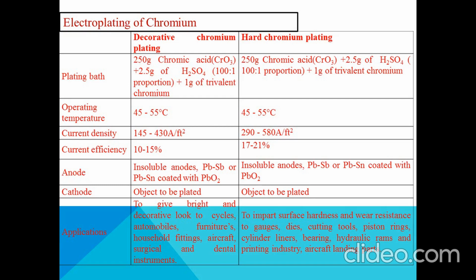In decorative chromium and hard chromium plating, the plating bath contains chromic acid and sulfuric acid mixture in the ratio 100:1. 1 gram of trivalent chromium is also added to that. Operating temperature in both the cases is same, that is 45 to 55 degrees Celsius. Current density maintained during decorative chromium plating is 145 to 430 amperes per feet square, and in case of hard chromium plating, high current density of 290 to 580 amperes per feet square is applied. Current efficiency in case of decorative chromium plating is 10 to 15%, and in case of hard chromium plating is 17 to 21%. Current efficiency means out of total current passed, how much current is used during electroplating. The anode used in both the cases is same, that is lead tin or lead antimony coated with lead dioxide. Cathode is object to be plated.